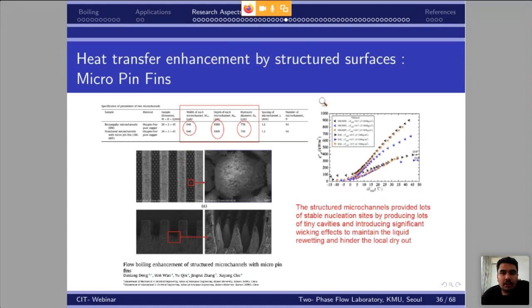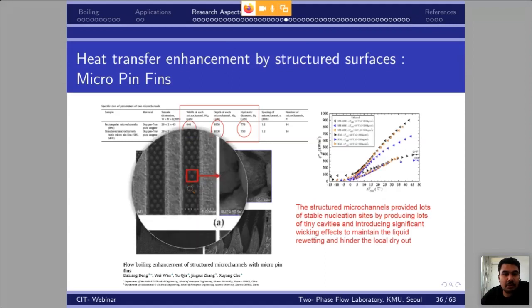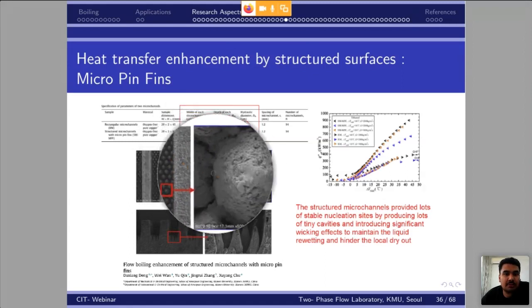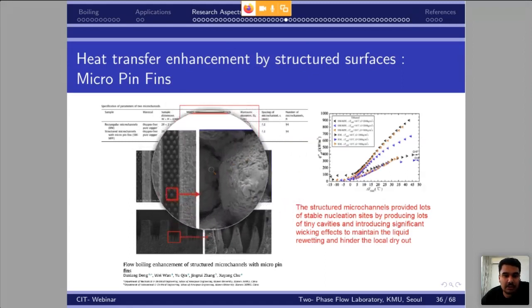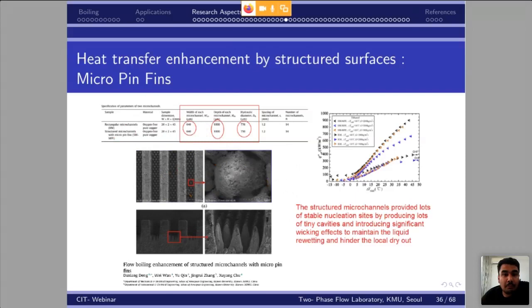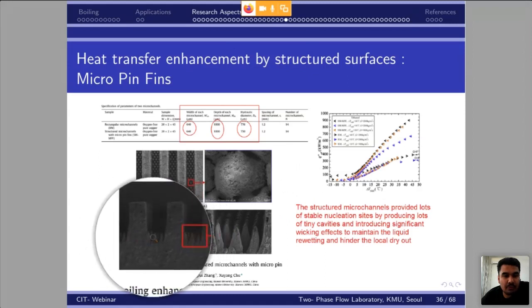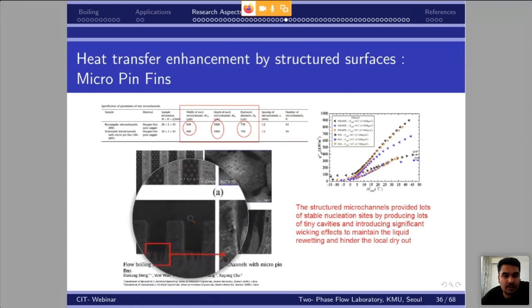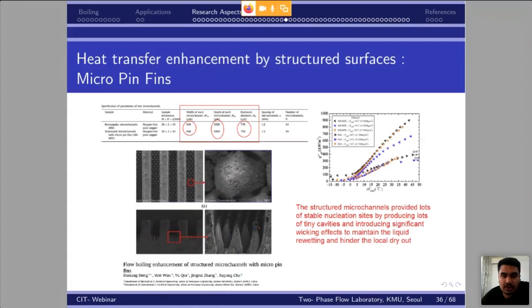Okay. The next method is heat transfer coefficient enhancement by using micro pin fins. You can see that by using laser machining and so on, we can create a lot of microstructures on the surface like this. You can see some microstructures. These structures will provide a lot of nucleation sites. A large number of nucleations can be promoted from the surface. You can see some fins, small fin surfaces on the channel. This is the channel surface. You can see small microstructures.